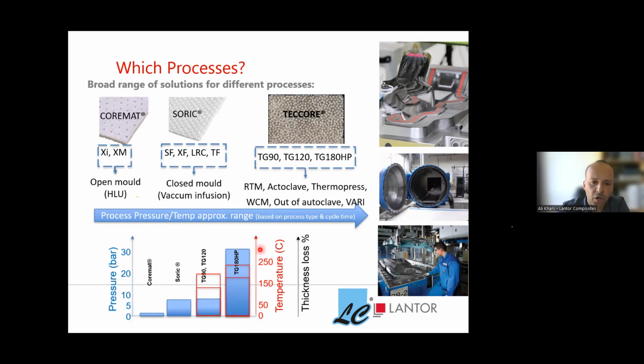And as you can see from this chart, I have compared the pressure and temperature resistance of these cores during process. As you see, the lowest is Coremat, then you have Soric, and then you have the Techcore variants TG90 and TG120. And basically the most resistant core under temperature and pressure is the TG180 HP. This resistance comes from the type of microspheres used in these products. For this TG180, the microspheres only become active when the temperature reaches around 180 degrees, and they can still be effective up to 220 degrees. So this is the range where microspheres are still efficient.